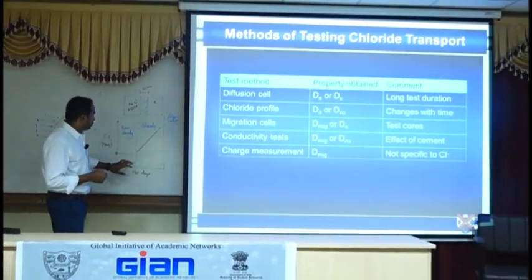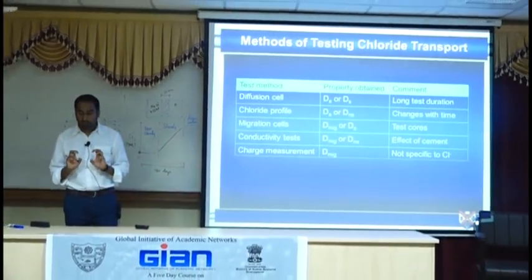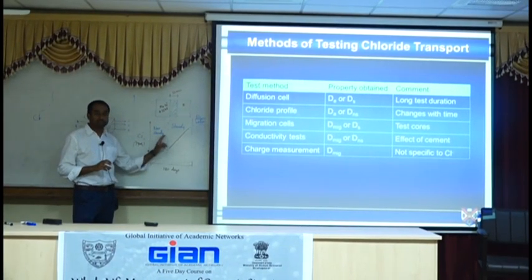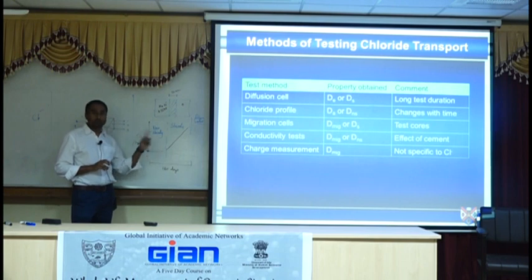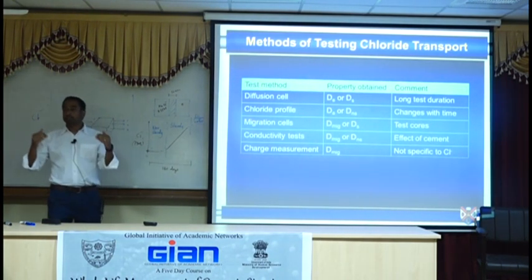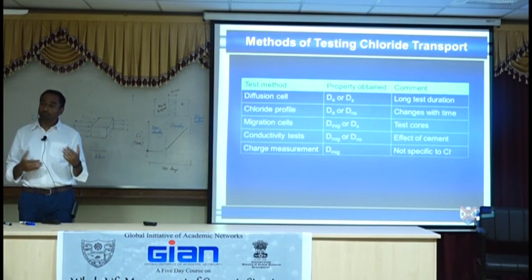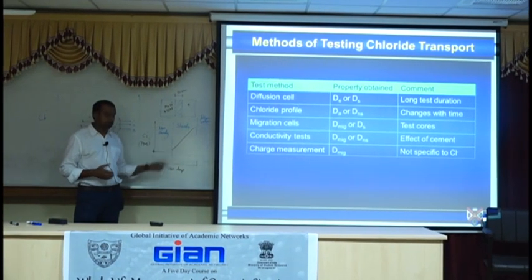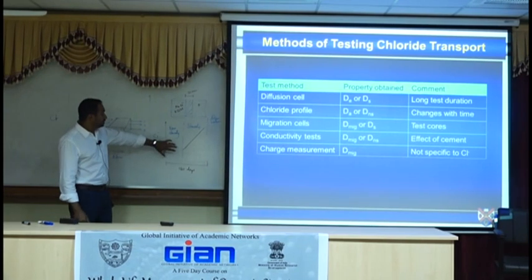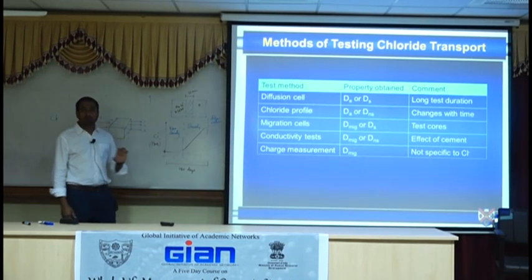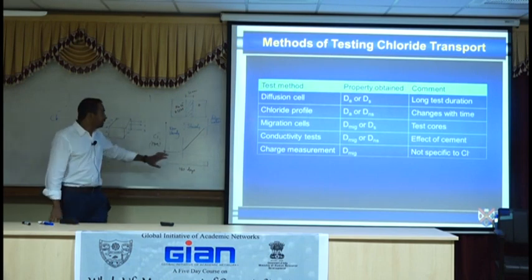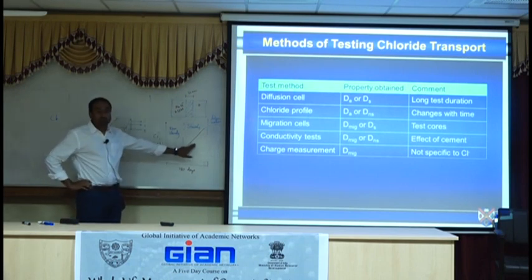Okay? All I wanted to highlight was just be aware of it, because depending on where you test and what observation you're expecting, your values will be different. Therefore, if you're to classify that certain concrete as good or bad, you need to know what that classification is from. Generally speaking, the values that you get here from standardized testing will be higher, of the order nearly 5 to 8 times higher than what you get here.